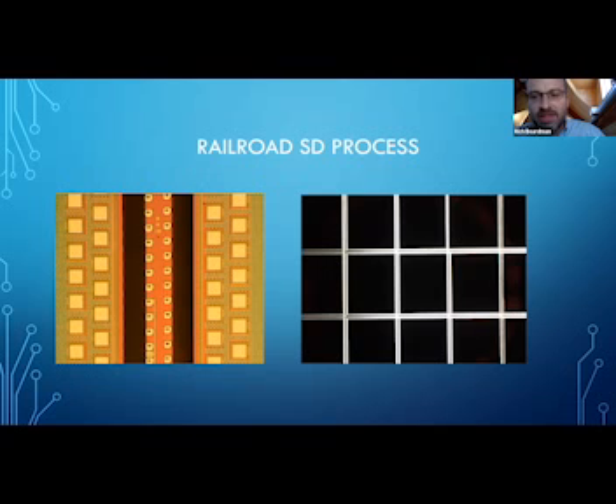And then we will leave that sliver of silicon within the street itself, and it would separate at the tape expansion step. Now, if we were to go narrower than 200 micron, what we may see is that sliver sticking to one side of the die or the other. So that's the downside to potentially doing this process. But down to around a 200 micron sliver, it works in production. It's a repeatable process.